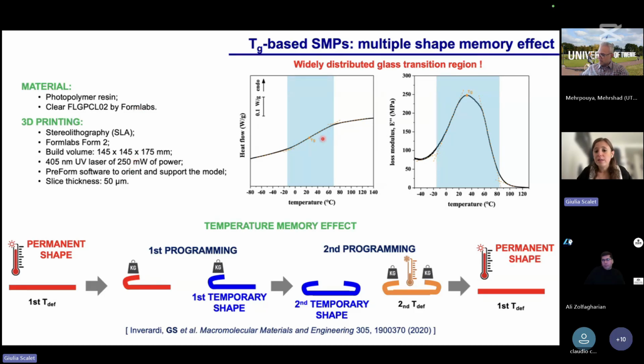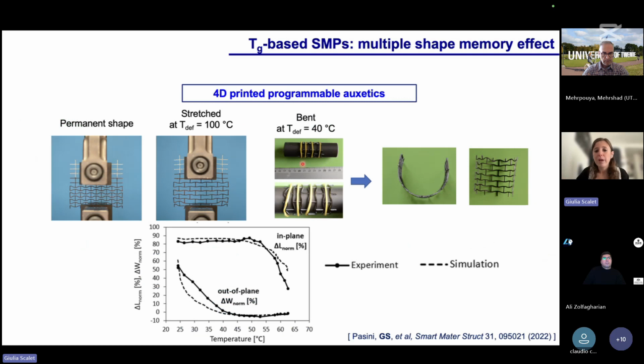This resin is very advantageous because it has a broad glass transition temperature that is a prerequisite for the so-called temperature memory effect. This effect is very similar to the multiple shape memory effect. So we have a permanent shape, different programming steps, and a recovery that is sequential, but the main important feature is that the material remembers the deformation temperature, so the temperature at which it was programmed, and this recovery takes place essentially at this deformation temperature.